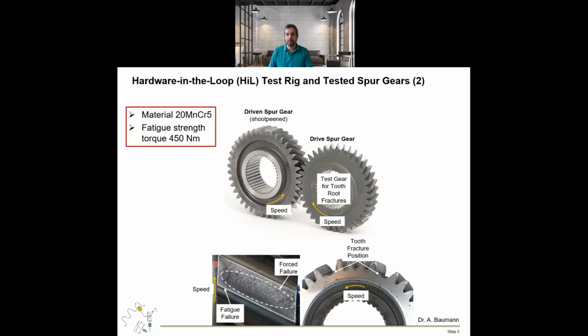On the downside of this slide, you can see a photograph of the fracture surface. The surface can be divided into two parts. First, we have the fatigue failure part of the crack, and in the middle you can see the so-called forced failure of the crack surface. In this picture you can see that there are two fracture positions, which indicates that the load on each gear tooth is equally the same in each test.